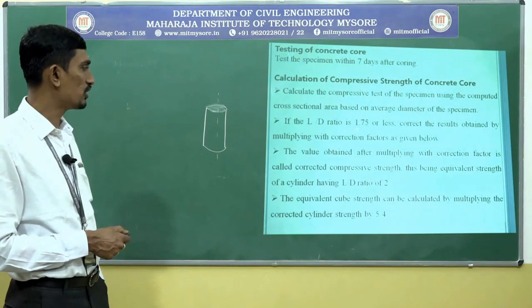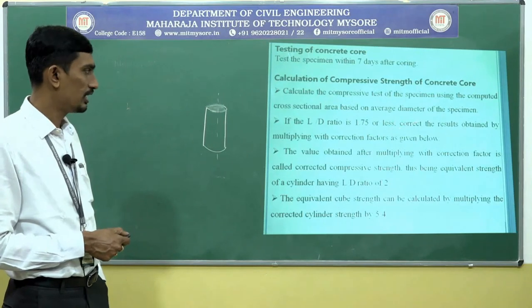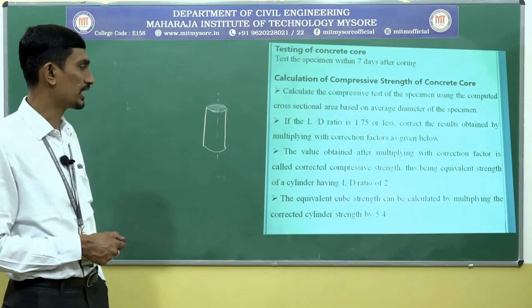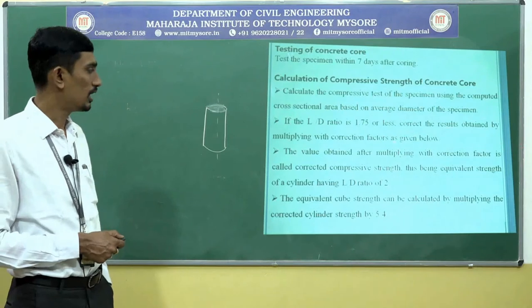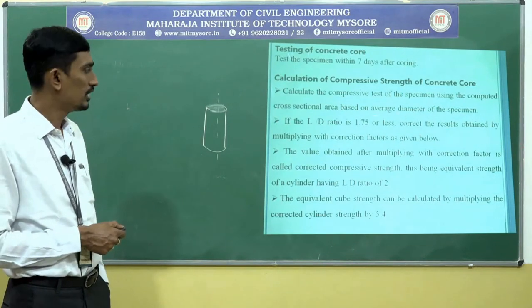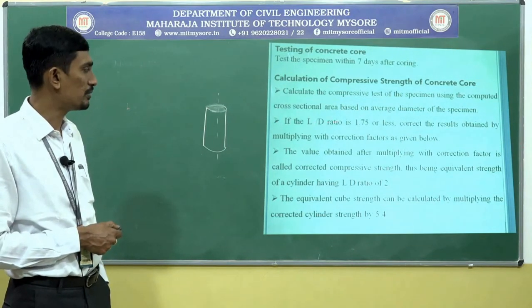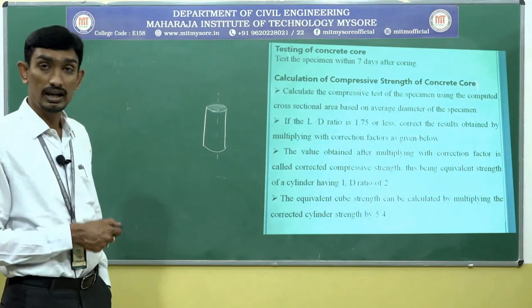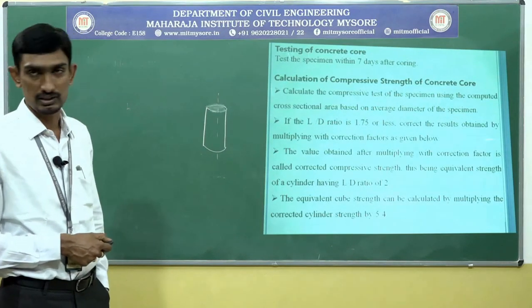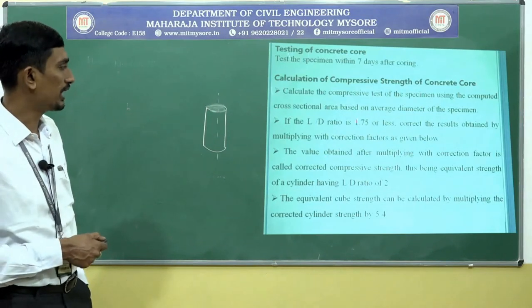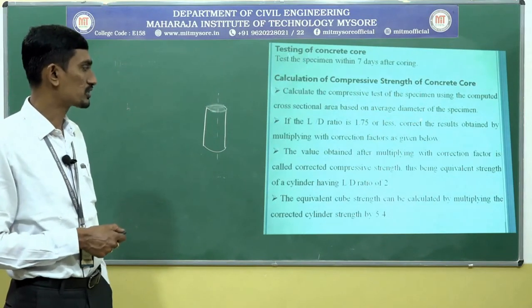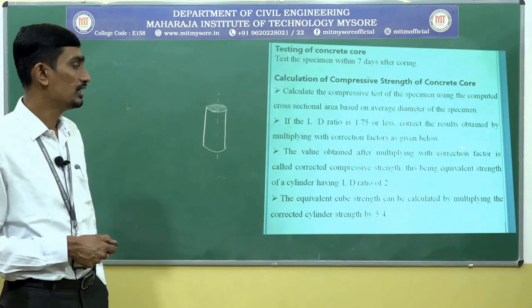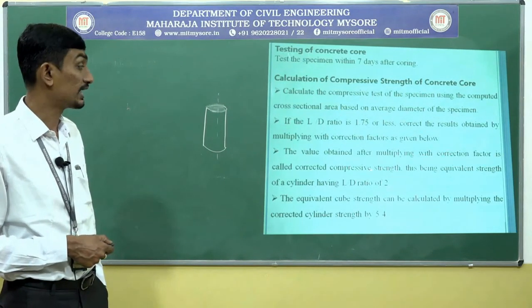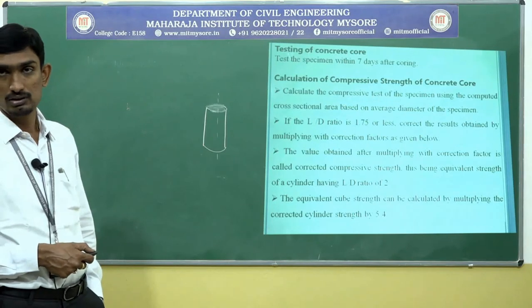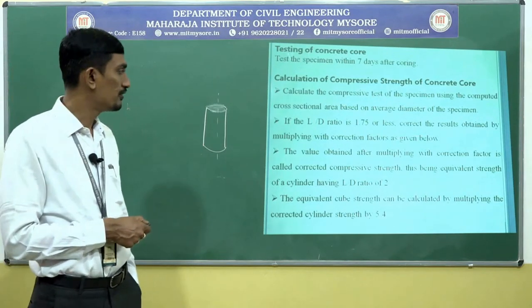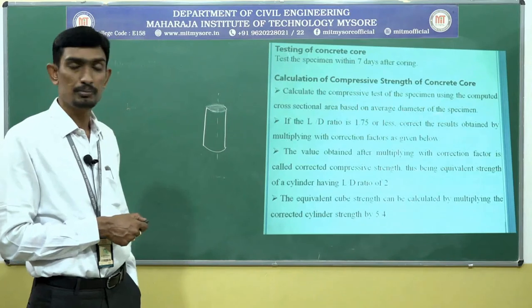If the L by D ratio is 1.75 or less, correct the results obtained by multiplying with the correction factor. I am going to show you what the correction factors are. If the L by D ratio, that is length to diameter ratio, is 1.75 or lesser, we need to go ahead with the correction factors. The compressive strength value obtained, multiplied with the correction factor, is called the corrected compressive strength.